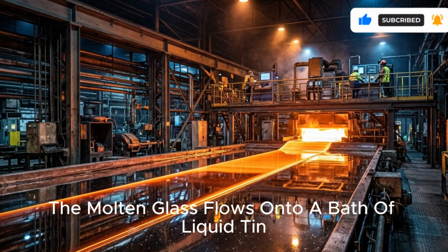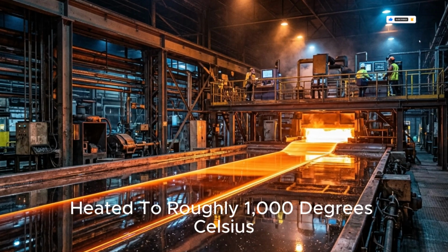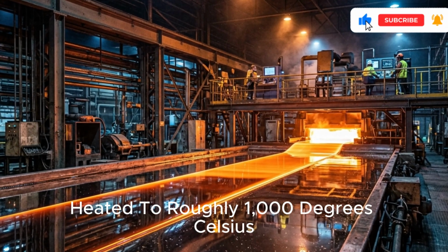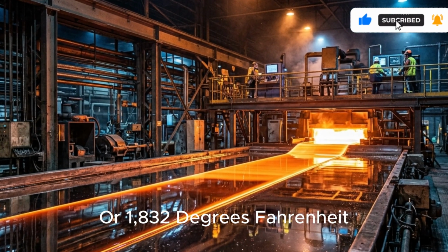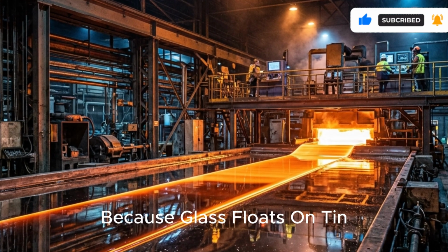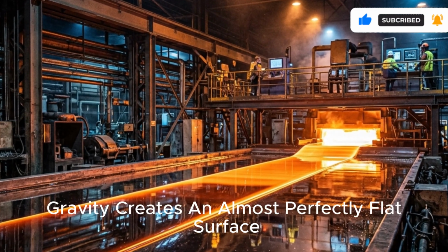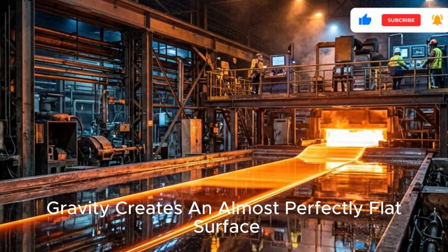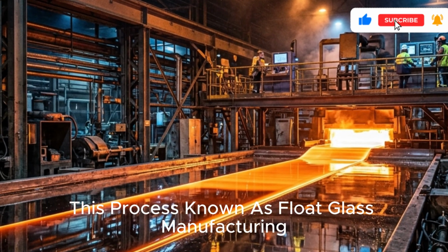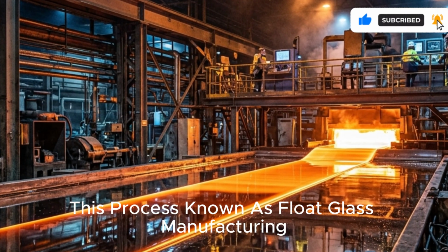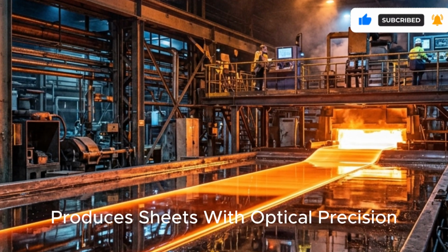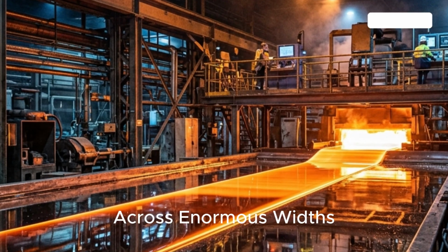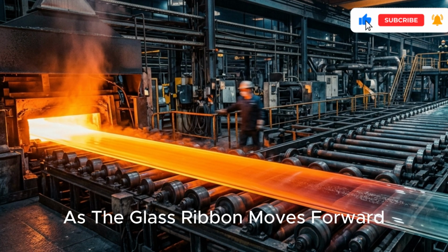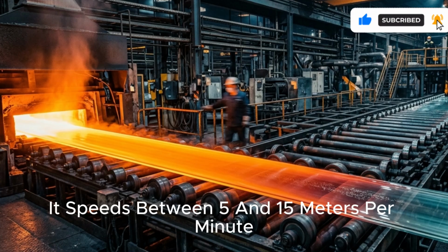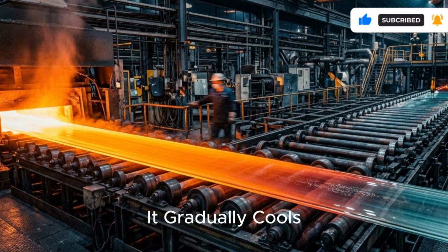The molten glass flows onto a bath of liquid tin heated to roughly 1,000 degrees Celsius, or 1,832 degrees Fahrenheit. Because glass floats on tin, gravity creates an almost perfectly flat surface. This process, known as float glass manufacturing, produces sheets with optical precision across enormous widths. As the glass ribbon moves forward at speeds between 5 and 15 meters per minute, it gradually cools.